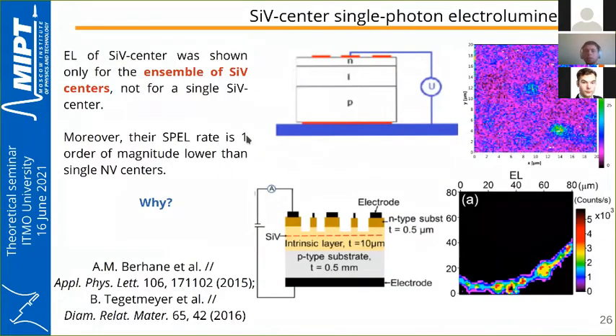These results allow us to explain the failure of recent experiments on the electroluminescence of silicon-vacancy centers in diamond. Electroluminescence of silicon-vacancy centers was shown only for an ensemble of silicon-vacancy centers, not for a single one. Moreover, the single-photon electroluminescence rate was one order of magnitude lower than for a single NV center. But considering it was only from an ensemble, it means that from a single silicon-vacancy center it was even lower.